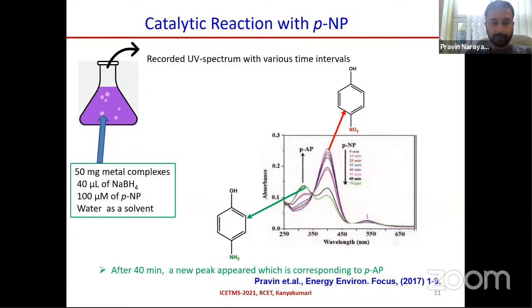So the reaction mixture contains 50 milligram of metal complex and 40 microliter of sodium borohydride, which is a reducing agent, and 100 micromolar of para-nitrophenol, with double distilled water used as the solvent. After mixing together, the UV spectrum was recorded at various time intervals, and you can see here